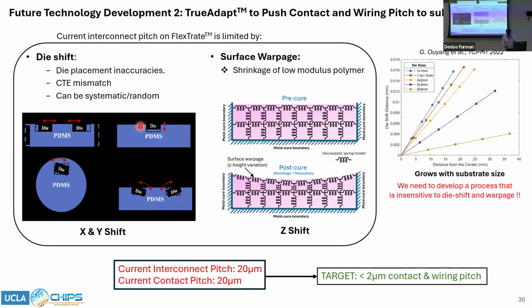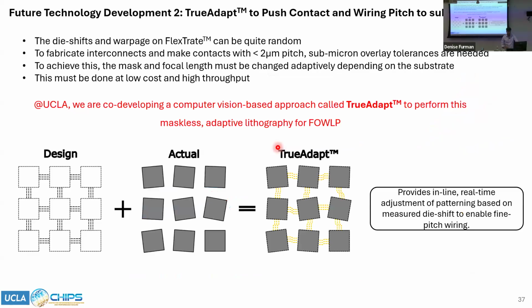So at UCLA right now, when we do 100mm wafers, because the polymer that we use has a low Young's modulus, these effects are not that significant, so we can still go ahead with the 20 micron pitch. But if you want to scale this to large scale wafers like 300mm wafers or panel scale, or push down the interconnect pitch to sub 2 microns, we need to basically do lithography accounting for these shifts as well as these kinds of warpages on the surface. And so the way we do this, and this is a process that's currently in development at UCLA, and something that I want to continue here at UT as well, is called TrueAdapt.